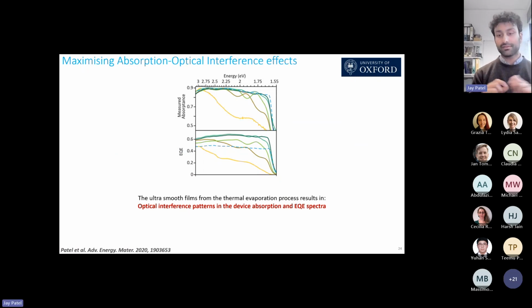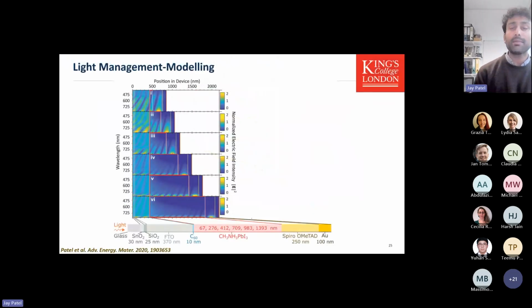When you form a thin film, you have a Fabry-Perot effect, and you form an internal optical field. The light goes into the device, reflects back off the metal electrode, and comes back. If it's not absorbed, you'll start to see a formation of standing waves, and you can see that here clearly. The thinner the device, the more of the light comes back from the metal electrode, and you start to see the formation of these standing waves. You really have to make sure that you tailor the thickness such that there are no standing waves and all of the light is absorbed effectively. So we did some light management modeling to understand exactly what thickness is optimal to absorb the most light, but also extract the best optoelectronic properties.